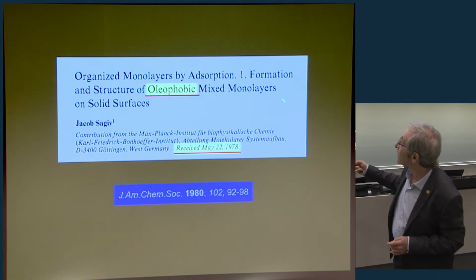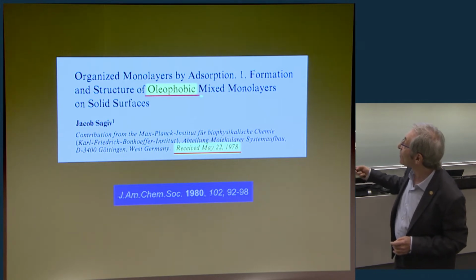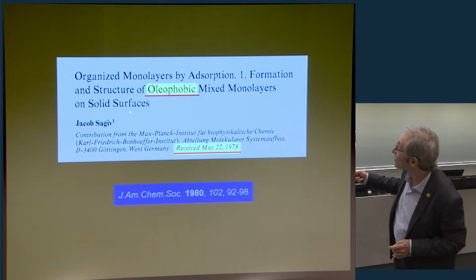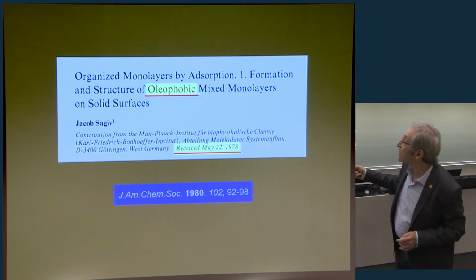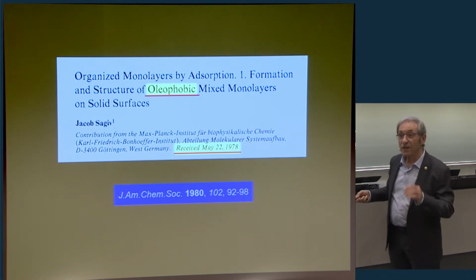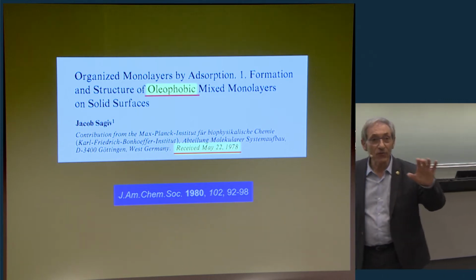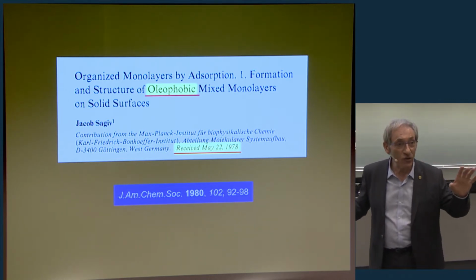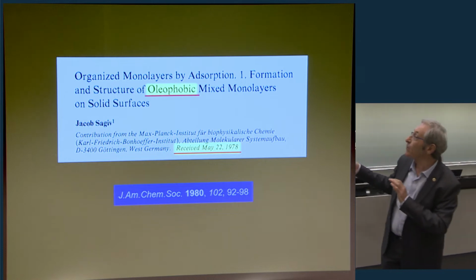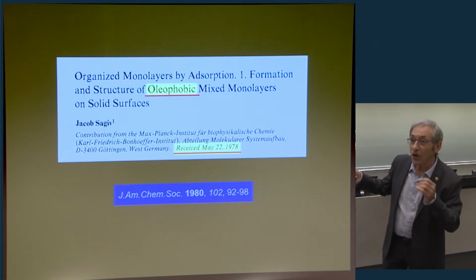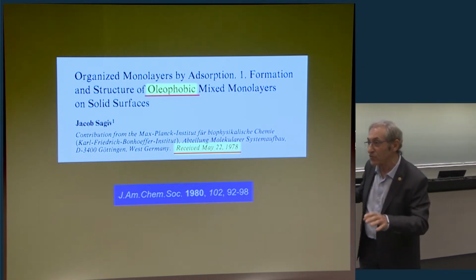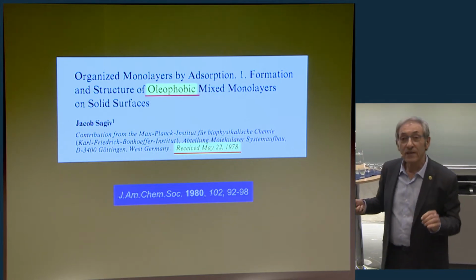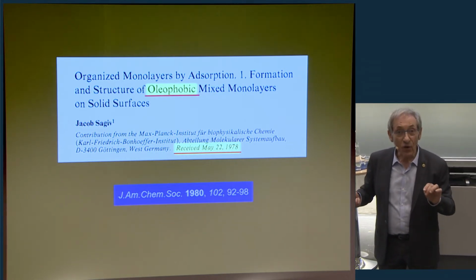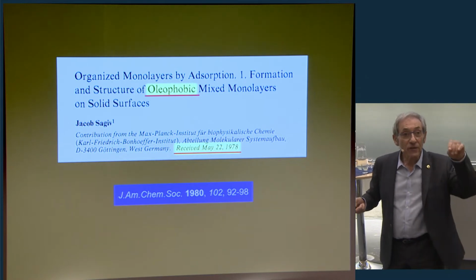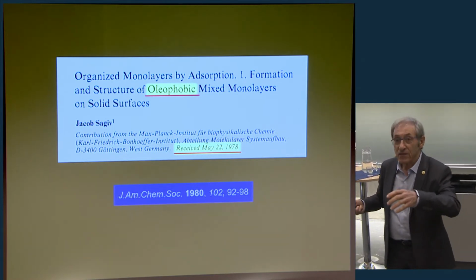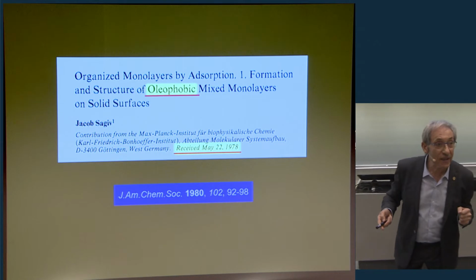And this is formation and structure of oleophobic mixed monolayers on solid surfaces. Now, the key word here is oleophobic. What is oleophobic? We know hydrophobic is repellent of water. So these monolayers also repel oils. It means that the monolayer forms from an organic solution, which is an oil, but once the monolayer is formed, you can withdraw the substrate from the solution completely dry.